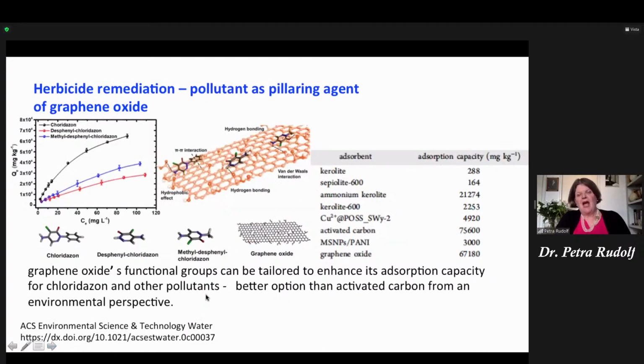So actually, what you can do now is to use it as a pillaring agent. So you expose the graphene oxide to the polluted water, and it is these molecules which will go in and which will attach to the graphene oxide. And actually, without any optimization, the sorption properties are already at the same level as activated carbon, which is what is currently used. And it is much cheaper than activated carbon, and the preparation is more environmentally friendly. So that is something that one will certainly work on also in the future, because if one tailors the functional groups a little bit, I'm sure that one can get even better absorption properties.